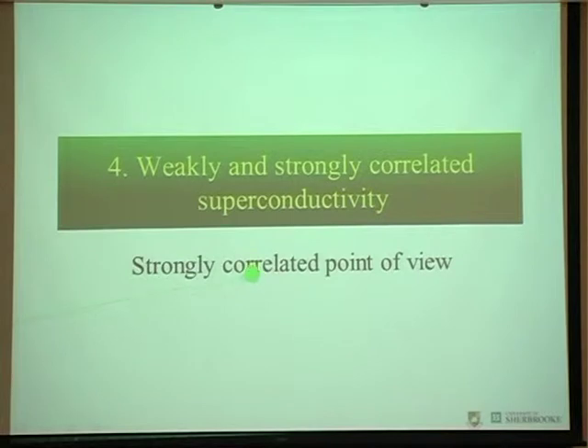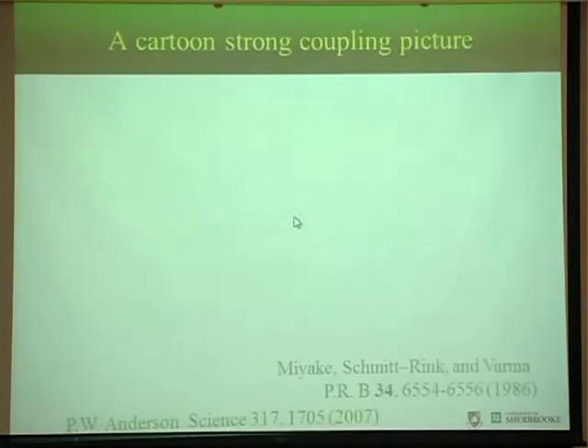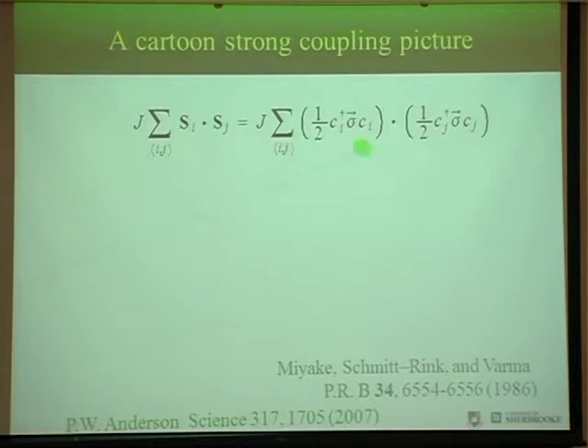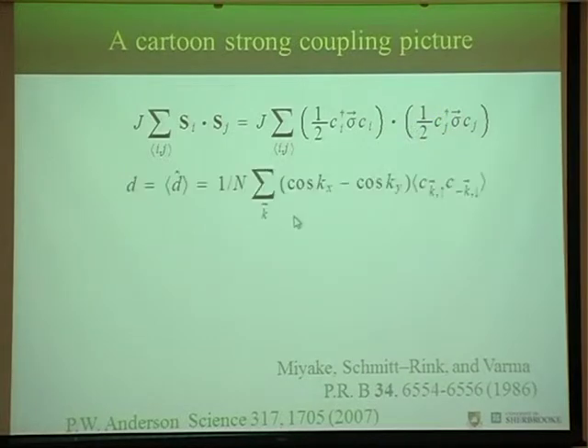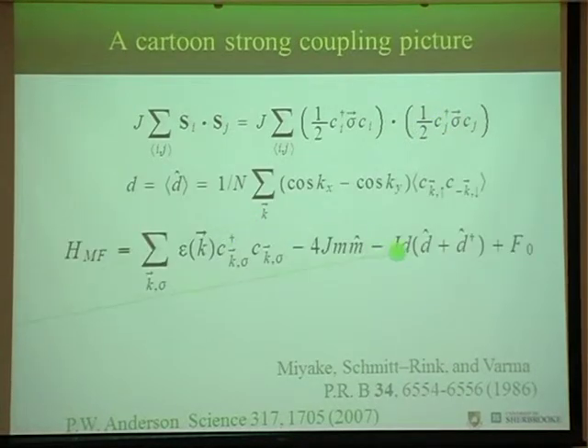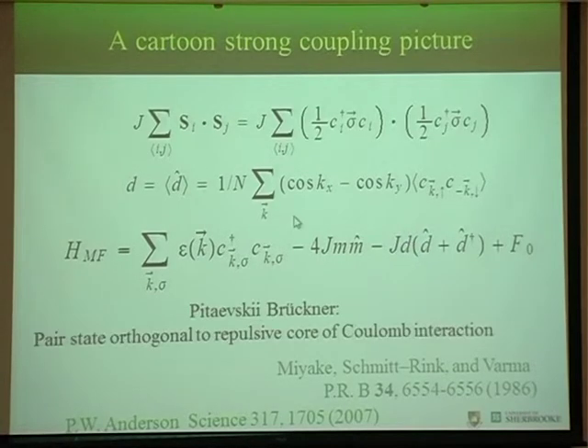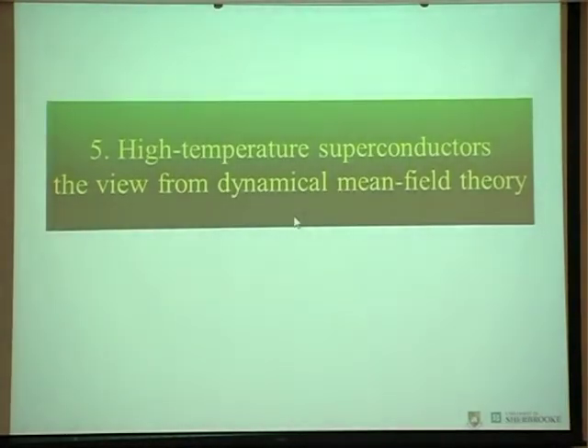Okay, now we look at the strongly correlated case. What is the mechanism when you have strong correlation? Well, the first one that was proposed, again, before the high Tc, is just to take the Heisenberg interaction and do an anomalous pairing of the c dagger c, like you do usually in BCS. And you find a mean field solution where J has a minus sign in front of it, so it is attractive for D-wave pairing. The idea is credited by Anderson to Pitaevskii and Brueckner, where the pair state is orthogonal to the repulsive core of the Coulomb interaction.